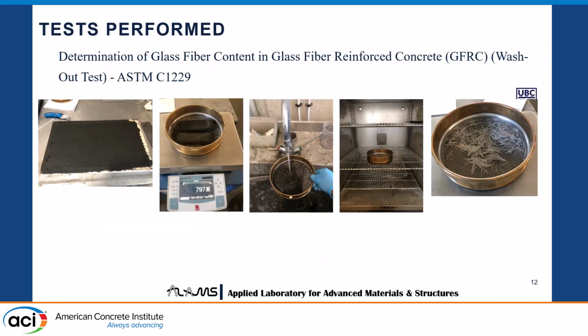And we also did the test for GFRC content in glass fiber reinforced concrete. This test is called a washout test following ASTM C1229. So for this test, two 6-inch by 2-inch coupons are cut from a freshly produced cladding panel, as we can see from the second picture. And then it's washed, then it's dried, and from the dried sample we can measure the amount of glass fiber.